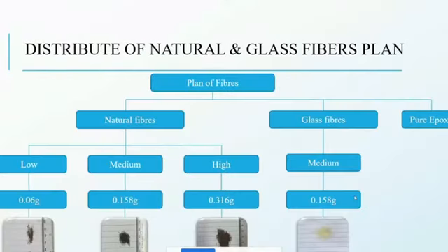In order to have a very good comparison for our study, we try to get the natural fiber from the palm tree, compare it with the glass fiber, and compare it with the pure epoxy without adding any kind of fiber. For the natural fiber, we use different weights. We start with low, medium, and high as compared to the weight of the sample. It's a weight percentage. And for the glass fiber, we only used one, compared to the medium, and we see how the result is going to be after doing the small punch test and the Brazilian and do some microscopic analysis for the fracture surface.